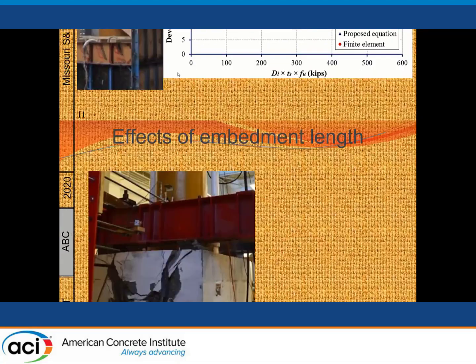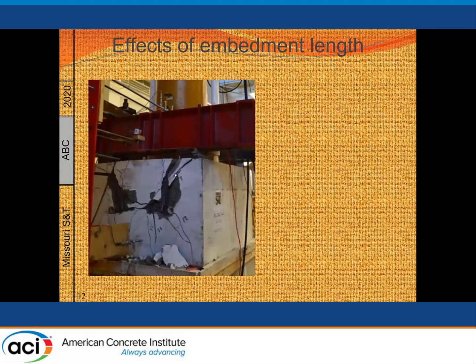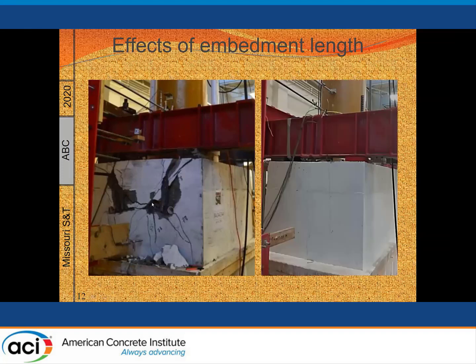So here is one of the columns where we did not provide the required embedment length. So we know before we start, this one was designed to have embedment failure. So as you would expect, over here, a typical failure in the column because of the pull out of the steel. And this is very much the same, but we provided enough embedment length. So you would see here the difference.